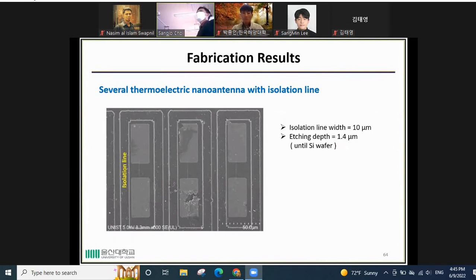And this is the several thermoelectric nano antennas with isolation line. So we can see this is the isolation line. This is the fabricated device. The isolation line width is 10 micrometer with an etching depth of 1.4. We etch into the silicon wafer to provide good electrical insulation.